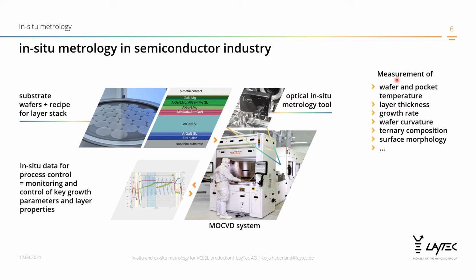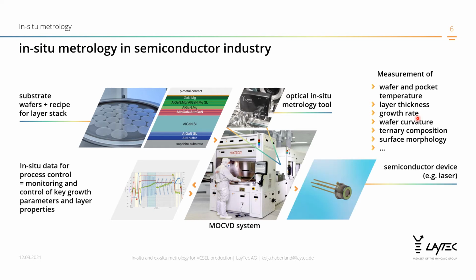And the measurement includes wafer and pocket temperature, layer thickness, growth rate, wafer curvature, ternary composition, surface morphology, and much more. And in the end, that is helping you to produce better devices such as lasers.